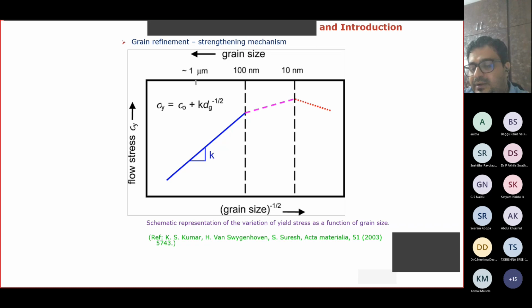For any given material, when you look at the grain size, it will not be of uniform size. There exists some kind of distribution. Therefore, you should always report the average grain size with an error bar that includes the standard deviation out of the statistics. And the moment that you reach 10 nanometer grain size, the grain boundaries become really unstable, and the existence of dislocations is really questionable because we cannot have a dislocation in such a small grain size.